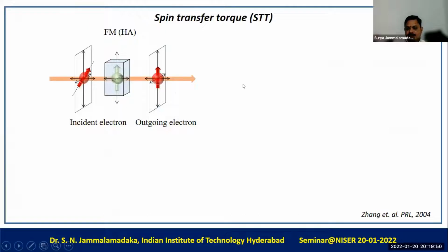So before I go into the details of the results, I would also like to introduce another important concept, which is called the spin transfer torque. Basically, when we send an unpolarized current through a spin polarized material, the current will be spin polarized. And when the spin polarized current passes through a ferromagnetic material where domains and domain walls exist, this spin polarized current will transfer momentum to the magnetic moments which exist in the sample. Because of the conservation of angular momentum, there will be motion of the domain wall. This is the basis for many domain wall motion devices.